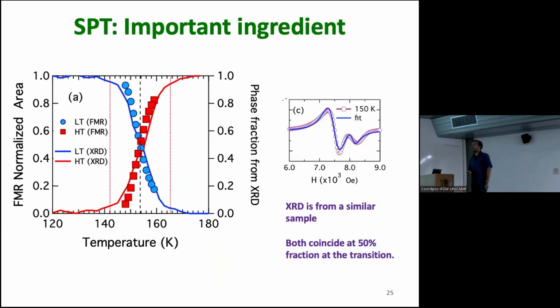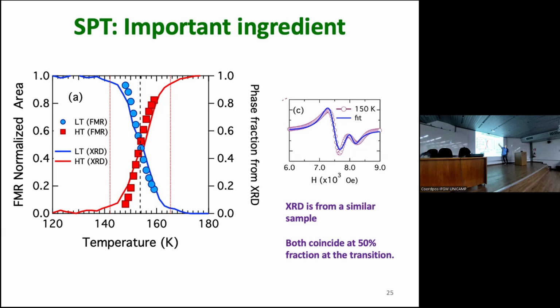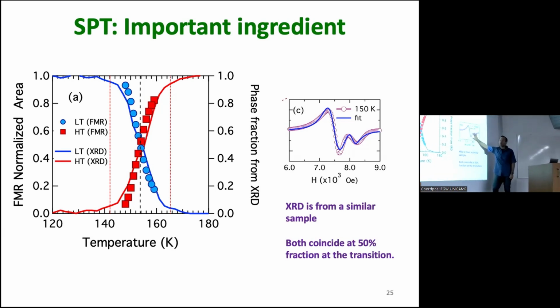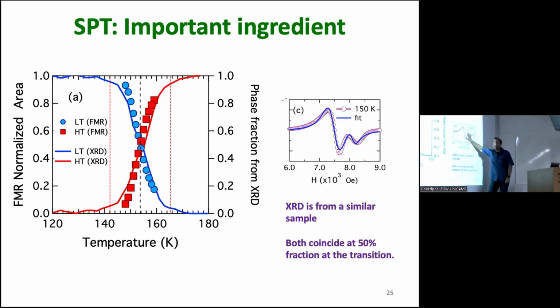Okay? So just to summarize this very quickly, we have looked into a way to calculate the phase fraction of the two resonances. So I can account for how much is the first resonance versus this one, and make a phase fraction. So how much is this versus this? At high temperature, this one is the higher, and this one is 0. And then at low temperature, this one is the maximum, and this one is 0.